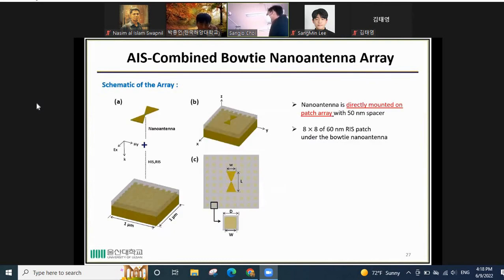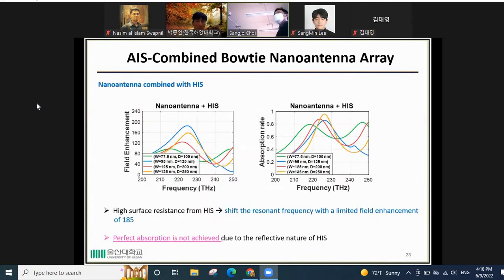After fixing the design of the artificial impedance surface, we combine the optimum design with the nano antenna array, and this is the schematic design of the array. As we can see, the nano antenna is directly mounted on the patch array with 50 nanometer spacing. In this design, we use 8x8 of the 60 nanometer RIS patch under the nano antenna. And this is the simulation results.